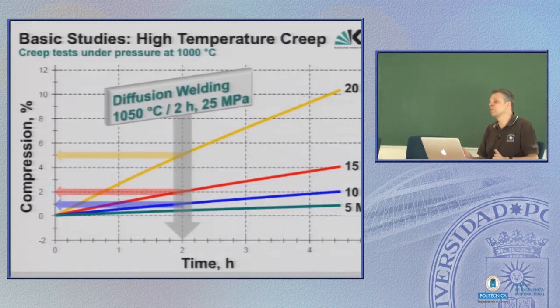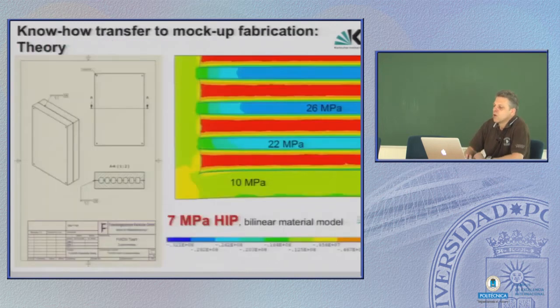In principle, for diffusion welding, you need very high temperature and very high pressure. Then the bonds will fuse completely together. But of course, if you have to take the creep into account, then you cannot use these very high pressures. So we transferred all these basic examinations into a mock-up fabrication. This was a small piece with, if I count correctly, 7 cooling channels as a closed box.